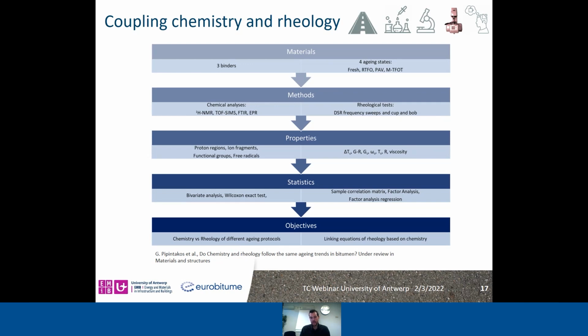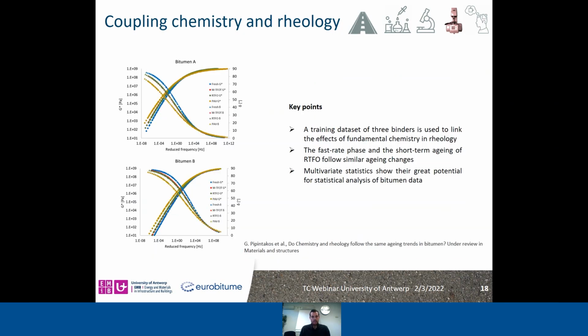Secondly, if we are able to link, somehow via a statistical framework, the changes in chemistry and rheology, taking into account aging. Changes in rheology are obvious. As you can see, for the two binders, there is an increase of complex modulus and a decrease of phase angle, and probably it's not completely obvious, but there is an overlap with RTFO, so the short-term aging as simulated in the lab, with the completion of the fast rate phase from the aging mechanisms.